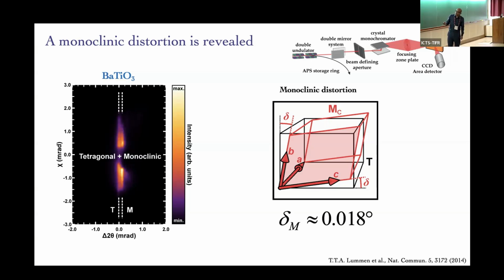And you can do a bunch of things. You can read this paper, and you figure out what this monoclinic phase means. It is simply, if you take the black cube, right, you have nice 90 degrees, you kind of skew it a little bit by 0.018 degrees. Very tiny. That's it. So as soon as you skew this, it's no longer tetragonal, and the polarization, that electrical polarization, does not have to be along the edge. It can sort of be anywhere in this plane. M, the mirror plane, only restricts the polarization to be in the plane anywhere. So that's one of the reasons you saw those shadows.